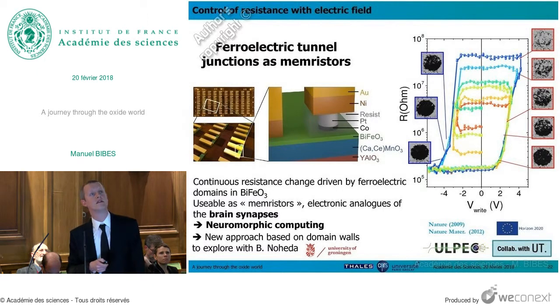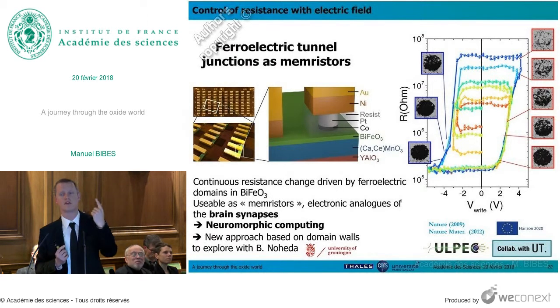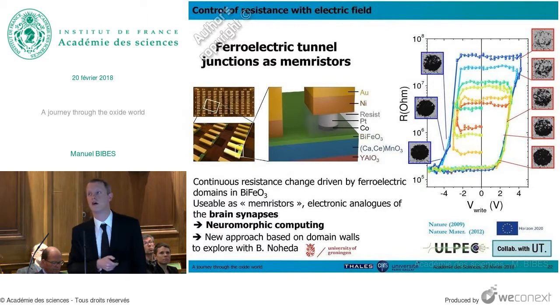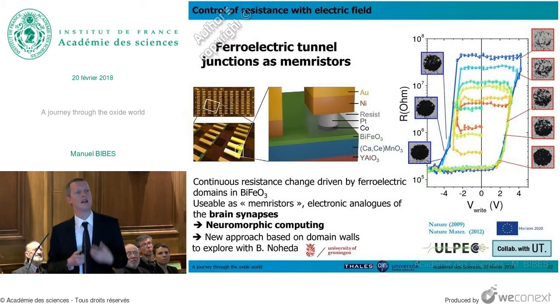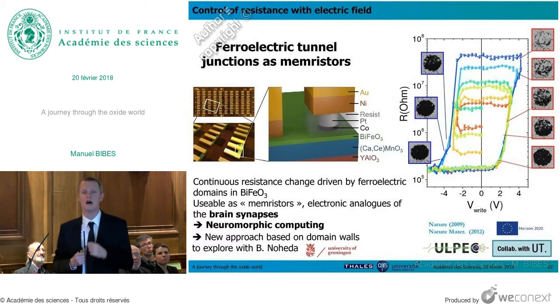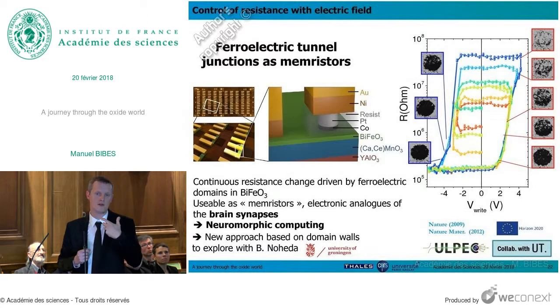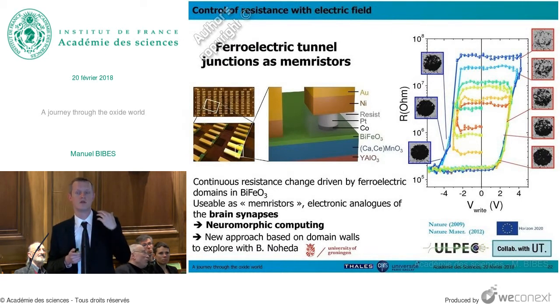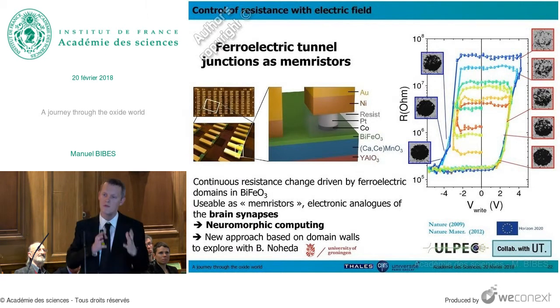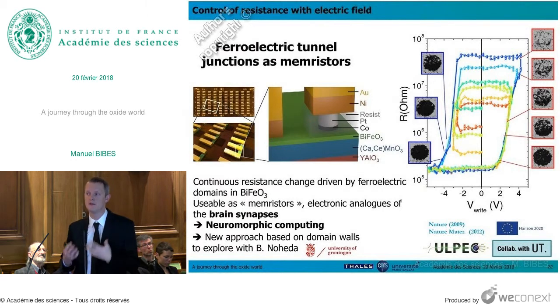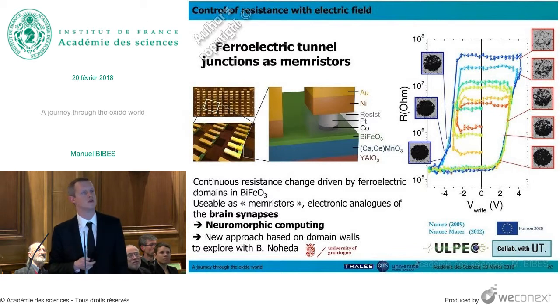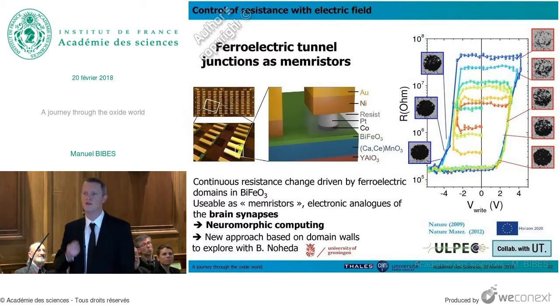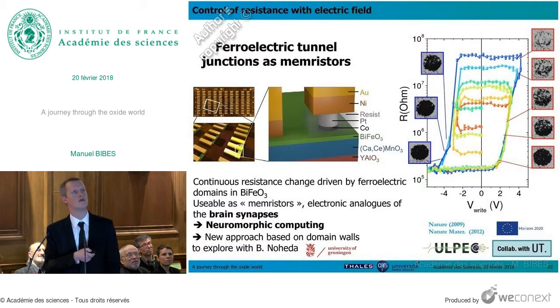And what's even more remarkable is that we have all intermediate states of resistance which correspond to situations where we have a mixture of domains with the polarization pointing up and pointing down. This corresponds to the gray and dark contrast here. And this qualifies these devices as memristors. And these memristors are electronic analogs of the synapses in our brain. And they are, of course, very important new devices for the development of new chips that would operate mimicking the way the brain works. So you can combine electrical neurons with electrical synapses and build a chip that would be an electronic analog of the brain to have very efficient computing. And I want to mention that the project with my colleague Beatrice Noheda in Groningen will be revolving around those ideas, but with new approaches, new concepts, again, using the material bismuth iron oxide.